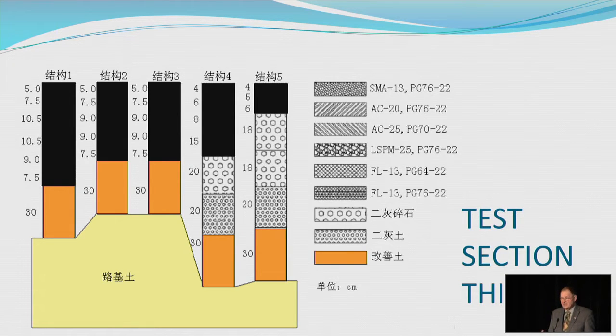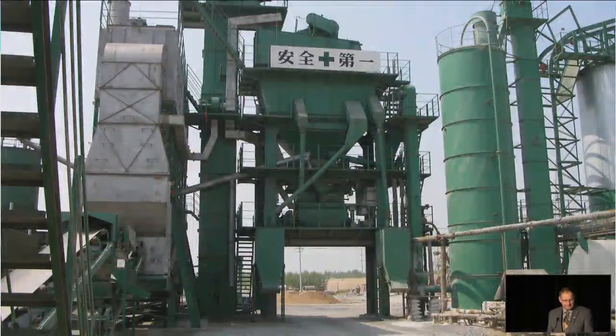So you'll notice that test section 4 has quite a bit thicker HMA, but still has the pozzolanic layers. Test section 5 has quite thin, about 6 inches thick, of HMA over top of cement-treated base.